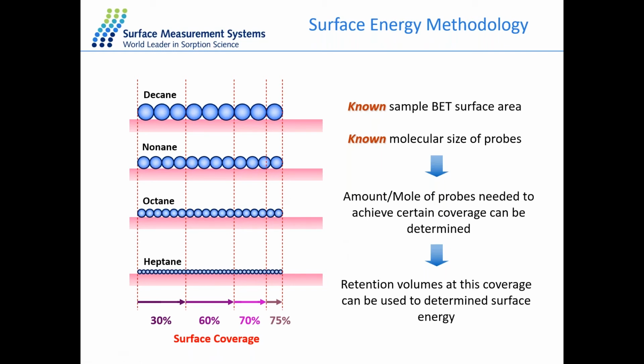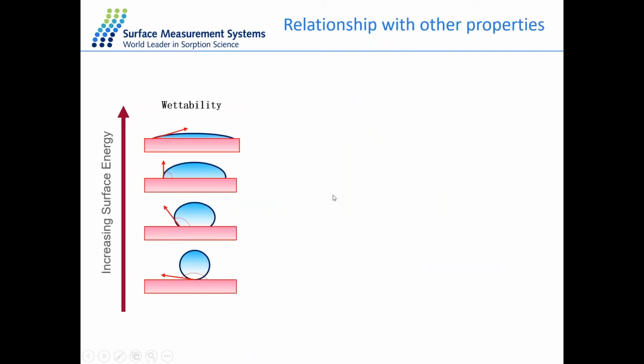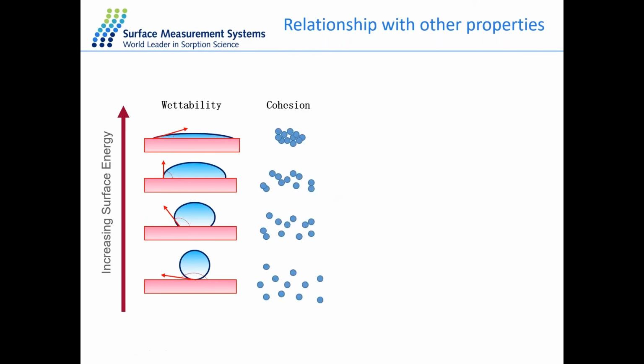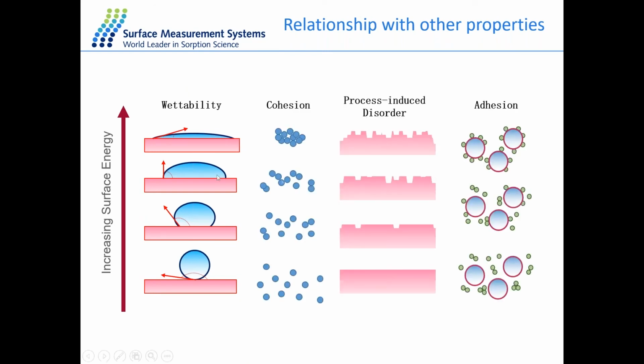As a result of the interaction between the probe molecule and the sample of interest, you will have different interactions based on the different types of probe molecules, and as a result, different retention times and volumes, which we can then go ahead and analyze. Surface energy is quite an interesting property because it can be related to other properties, one of which is wettability. If you increase surface energy, you would also get an increase in wettability. You also get an increase of cohesion. This is how likely the particles are to interact with themselves.